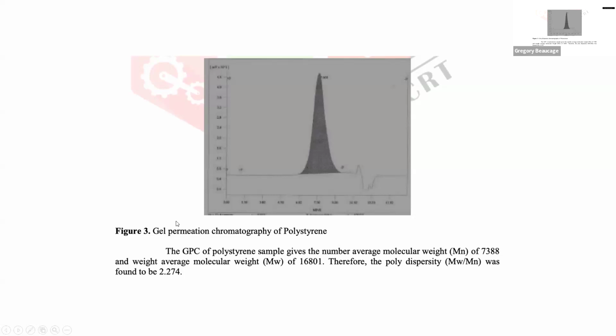A lot of times, to get polydispersity, they put two different catalysts into the reactor, right? And they'll be producing two different molecular weights at the same time. Then you can also have this kind of backbiting mechanism where the chain more or less doubles in molecular weight. So you can have one peak that's the main stuff you're making, and the high molecular weight one would be a doubling of the molecular weight. So a lot of weird things can happen.